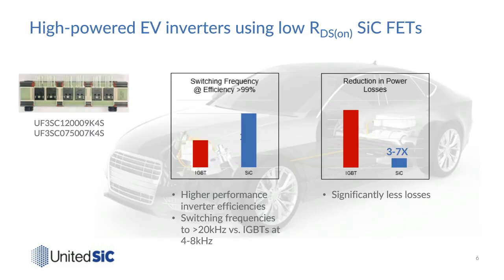And the primary thing that you can do with this is put it into use in applications like a traction inverter. So we've got examples where people have built traction inverters using 2 to 4 of these devices in parallel per switch position. And they bring you big improvements in efficiency because the switching losses are very low, of course, but the conduction losses are really extremely low. And like the previous speaker said, when you're running at light load, especially, the reduction in power losses is very significant. So it's about 3x at full load, and it gets up to 7x when you're operating at light load. So this is beneficial for traction applications.